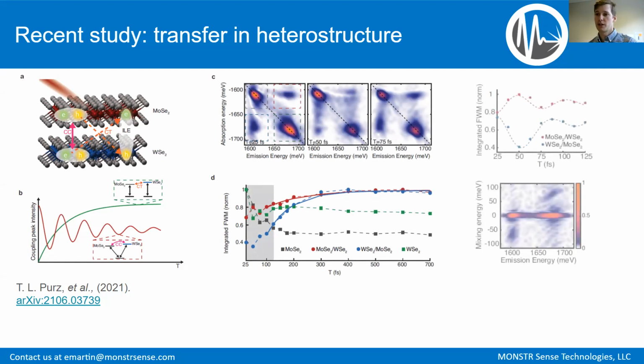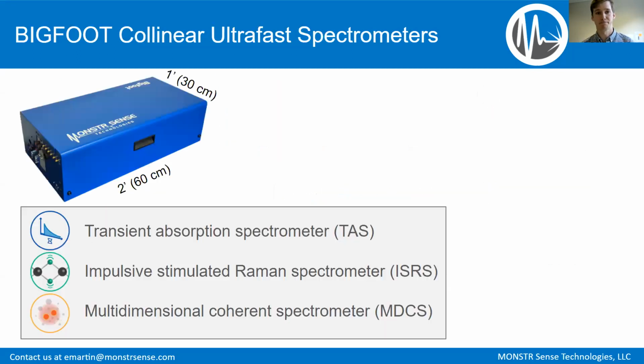And so at short time scales, so under 100 femtoseconds, you can actually see an oscillation. That oscillation corresponds to coherent coupling. The decay corresponds to charge transfer. And so they were able to tease out what the coherent coupling timescale was, what the charge transfer timescale was. All that information was written in here into the data.